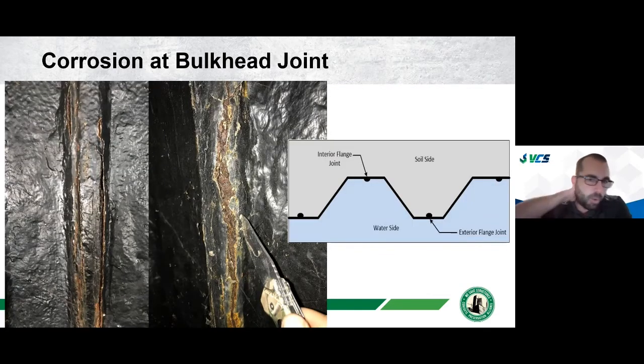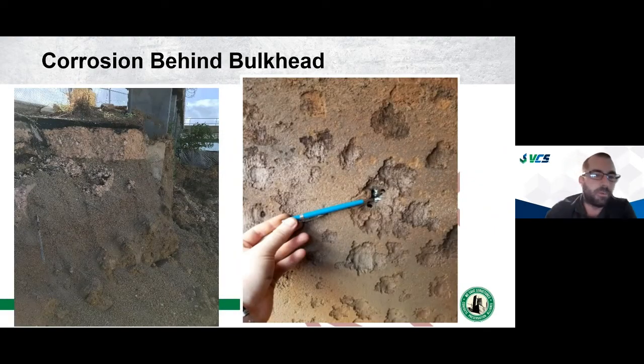And so, on the water side, they were seeing pretty severe corrosion at the sheet pile joints. So in the tidal zone, they had a coal tar epoxy coating, but you can see behind the coating, you see pretty serious corrosion at the joints in the flanges. And they were doing some upgrades to the wharf, and they'd done some excavations to install some things. And so when they did some excavations, they identified pretty serious corrosion pitting on the backside of the bulkhead. And they didn't know why, because they had an ICCP system.